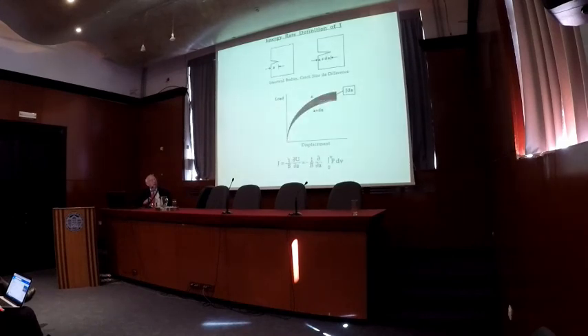So in the laboratory, the energy rate approach that Rice has developed was used. Two cracked bodies with identical cracks, except they differ by a dA. Then under the load displacement curve, the difference between the two curves, the one with the crack length a, the one with the crack length a plus da, the area between that is the J times the dA. Or you can represent it as a differential of an integral, as shown down below.